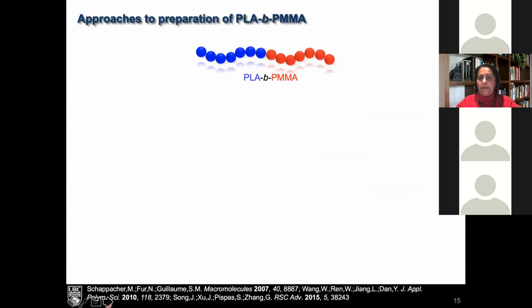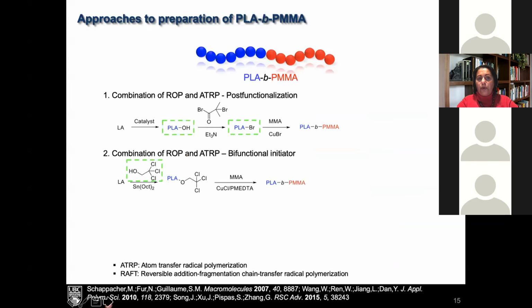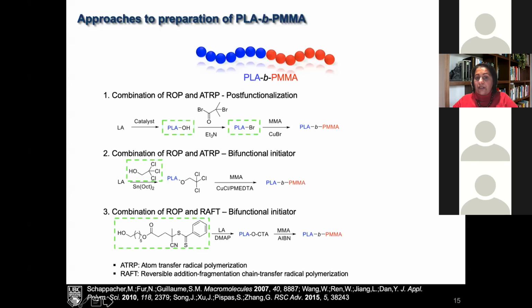How have these been made before? They've been made before with a combination of ring opening polymerization and atom transfer radical polymerization, where you can polymerize your lactide and you end up with a hydroxyl chain end, at which point you use an ATRP reagent, generate a halide, and then you use a copper catalyst to do methyl methacrylate polymerization. You can combine ROP and ATRP using a bifunctional initiator. You can use combined ring opening polymerization and RAFT. So you have to have a bifunctional initiator, and then you can use the reversible addition fragmentation chain transfer radical